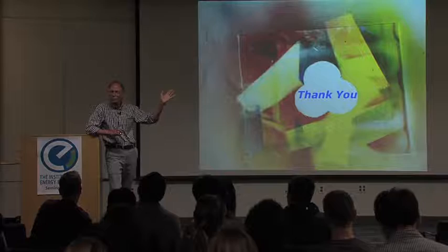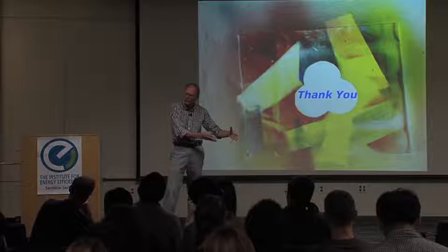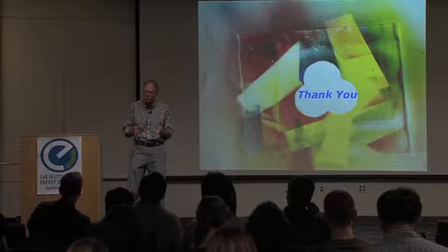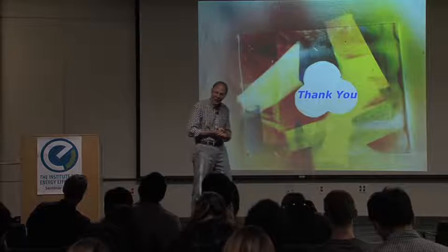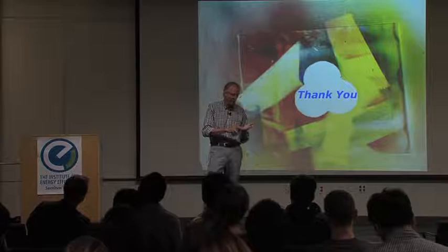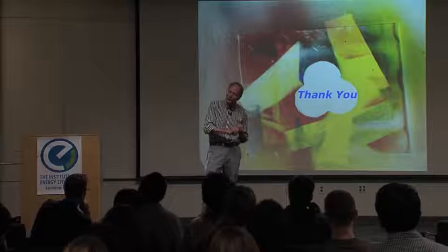And if you think about the kinds of applications that you would want, if you're going to be talking about a disposable, a few hundred to 1,000 is a good place to be. If you're going to be talking about, say, glasses or something you want around for a few years, then 10,000 is where you want to be. So really, it's been a materials-limited problem where the people involved in electrochromism have not developed the proper colors and materials that we've been working on. They've been using metal oxides, which are fine for windows. They're blue, they're slow, they're very durable, they do what they do. They've worked on viologens, which are blue or green. But this ability to get to the whole color palette has not existed until now with this kind of set of materials.